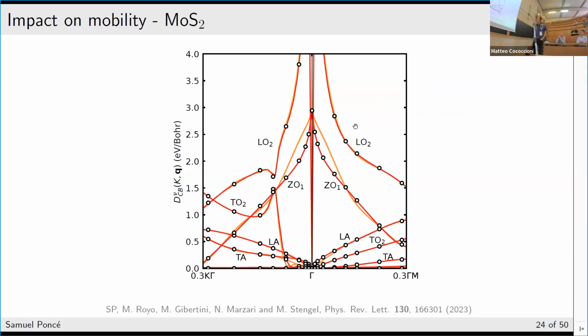If you zoom in, so this is another material, but it's the same concept, it's MoS2. If you zoom in, you can see that there are some small differences. So for example, those are the out-of-plane modes. And if you only include dipole, then you see that you don't recover the exact dispersion, okay?